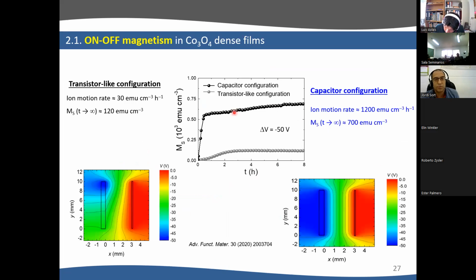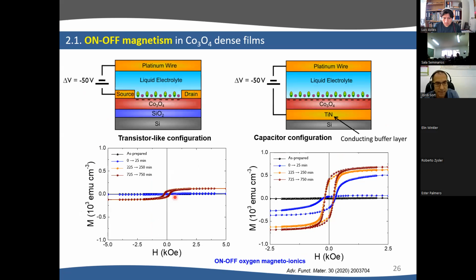Actually, you can see here the two configurations, the capacitor configuration and the transistor-like configuration. You can see that for the capacitor, MS increases fast and then saturates. For the transistor, it takes time and the amount of generated cobalt is much smaller. This can be understood from using COMSOL simulations because in the case of the capacitor configuration, the whole layer is affected by the electric field because it is grown on top of this titanium nitride, which is conductive. But in the transistor-like configuration, the electric field is just accumulated at the place we make the contact, so basically here, where we apply the voltage. And therefore, it is limited a little bit. The lateral movement of oxygen is limited and the effects are much smaller.